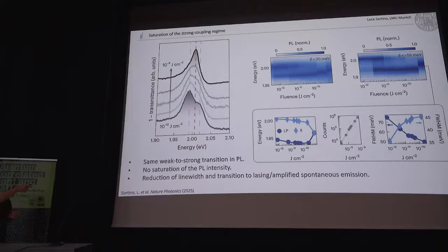So two peaks, where we have a strong exciton as the upper polariton, basically degenerate with the exciton at room temperature. But we could observe that as we increase the power for different detunings, we would always see this collapse of the emission into a single peak, mainly. We then looked at the position of the peaks. You see here that they collapse, but also with a redshift, so mainly related to a sort of phase space filling.